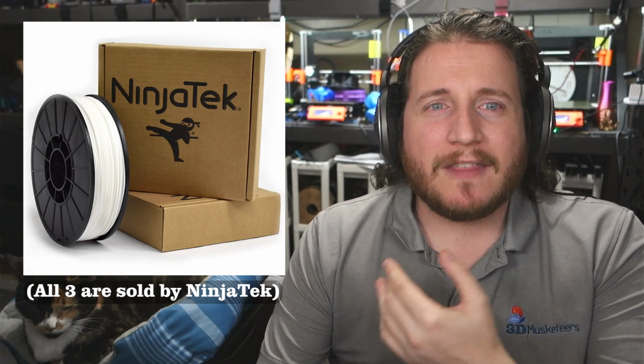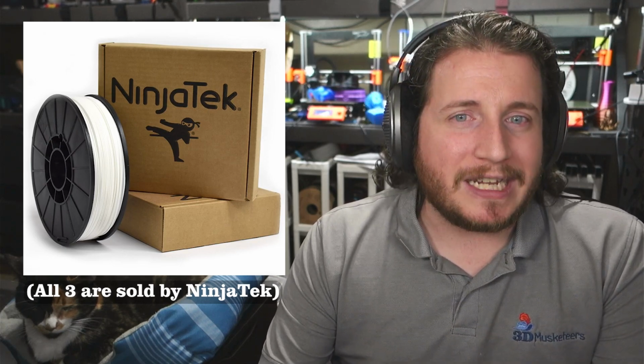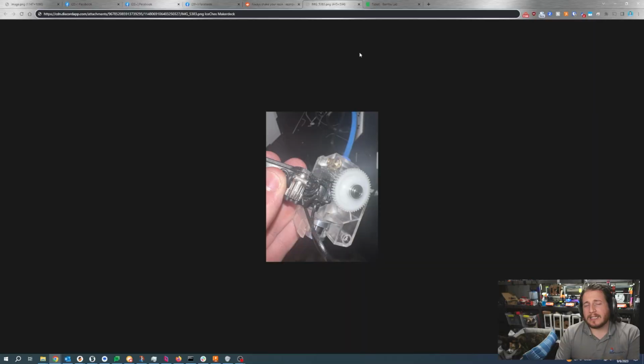And I know that there are materials out there like Ninja Flex, Cheetah and Armadillo that are a little bit easier to print than your bog standard TPU, but they're really expensive too. I buy a lot of the cheap stuff I find online, and it does okay when you dry it for a while. So bonus points if you do have a dryer. If you don't, I might hold off on printing TPU for a little bit because these failures can be common. We also find that less extruder pressure is better than more, although it will absolutely vary for your particular use case.